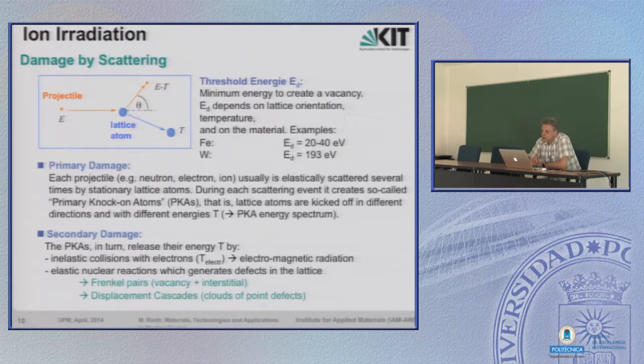During each scattering event, it creates so-called primary knock-on atoms. These are the atoms which are kicked out of their lattice sites. And so lattice atoms are kicked off in different directions and with different energies T. These PKAs, primary knock-on atoms, are then available in a multitude of very different directions and energies. That's the PKA energy spectrum. The secondary damage then is produced by the PKAs themselves.